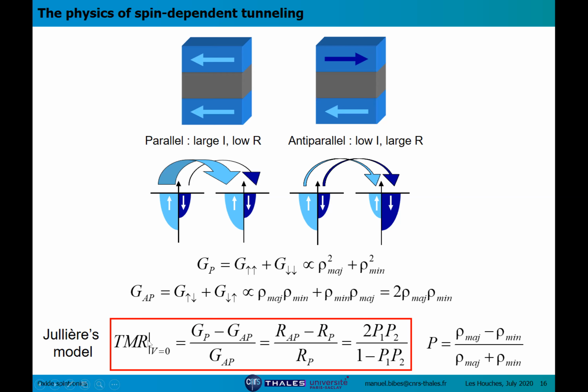This formula states that the TMR, defined as follows: you measure the resistance in the anti-parallel state and in the parallel state, you make the difference, and you normalize it by the resistance in the parallel state at high field. That's the TMR. And this is related to the spin polarization of the electrodes. The spin polarization, as I've mentioned before, is the ratio of the difference between the density of states for spin up and spin down, normalized by the sum. So if you know the spin polarization of a ferromagnet, you can directly estimate the TMR that you can get with it. Or conversely, if you measure the TMR in a magnetic tunnel junction, you can extract back the value of the spin polarization.